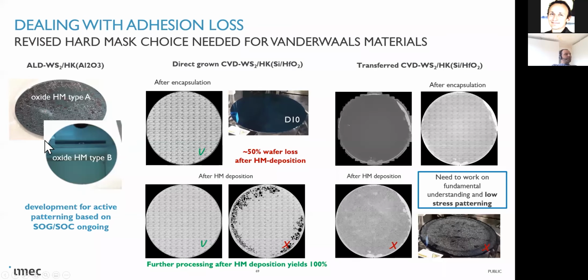And it can really pop up in every step, that the van der Waals bond can really change the whole behavior. And if you want to do CMP steps and building back end of line structures on top, there is a lot of temperature stress and integration stress that these wafers are seeing. And it's really a problematic thing to understand what is really driving these adhesion mechanisms and so on. So again, interface control will be very key, and we need to substantially improve that.